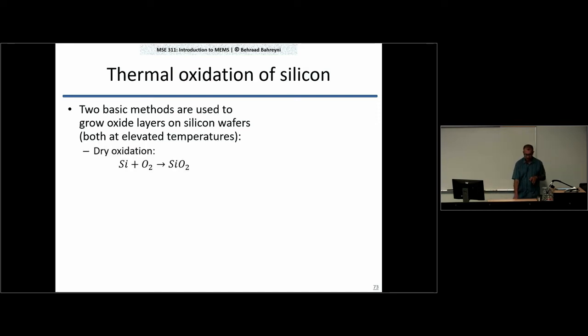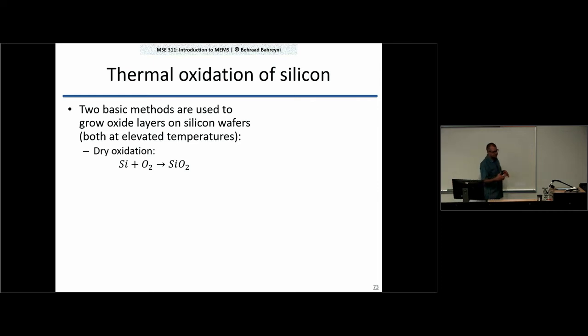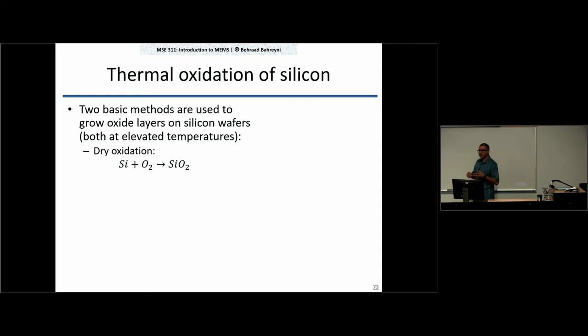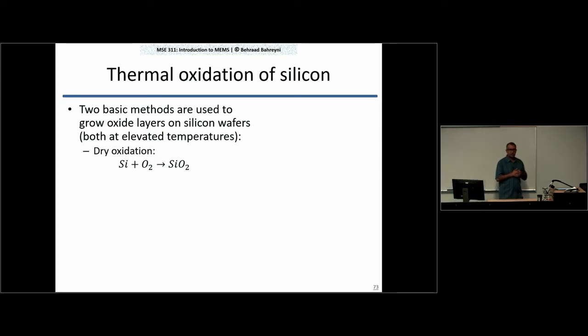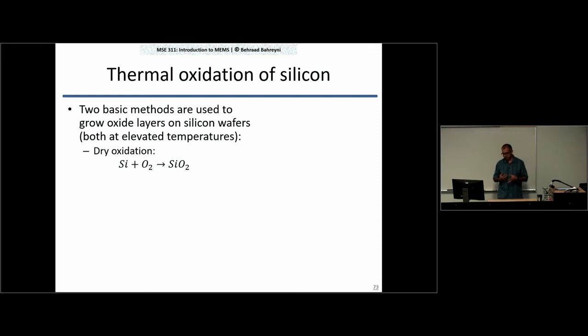There are two basic methods for growing silicon dioxide from silicon. The first is dry oxidation, where you bring an abundance of oxygen to the silicon surface and allow the two to react and form silicon dioxide. This doesn't happen at room temperature — you get the native oxide and everything stops. To grow a deeper layer you must elevate the temperature, typically between 800 and 1100 degrees Celsius, providing enough thermal energy to make the reaction between silicon and oxygen proceed.